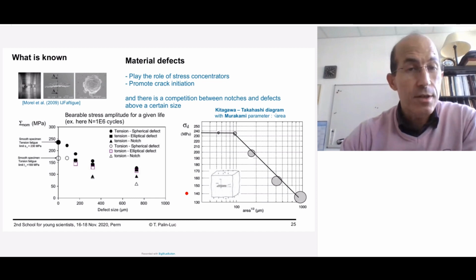But in real components, there are also defects, and the defects, as I said, are also a micro notch, geometrically speaking or mechanically speaking, where there is a notch like that, a micro notch with a scale here of typically 200 micrometer. This notch can also exist at the root of a macroscopic notch, or at the root of the gear's tooth, for instance. There is a competition between the stress concentrations, which promote crack initiation, and the defects.